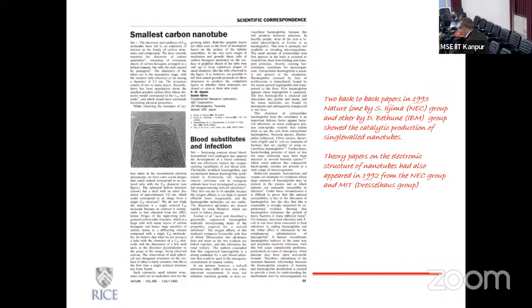And also, the nanotube was very unique because of the structure property correlations. The fact that you can have a small chirality in the lattice gives it very different properties, all the way from a semi-metallic carbon to semiconducting nanotube. It was a remarkable thing. And again, it is one of those milestones in nanotechnology, suggesting that you can actually tweak the structure a little bit and get a significant change in electronic properties.